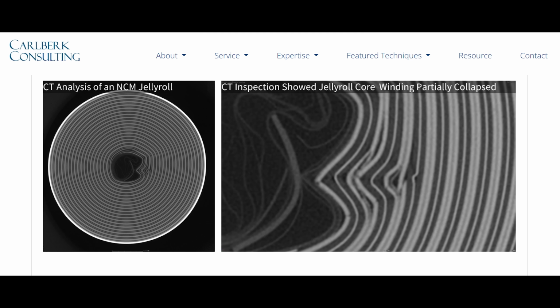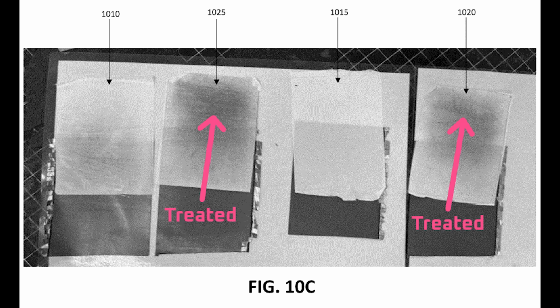If the electrolyte was able to wet the electrode without those pressure changes, it could maintain the pore integrity and therefore stiffness. Second, that whiplash could also push and pull on the inner spiral of the jellyroll. That, again, could be avoided by reducing the vacuum and electrolyte injection pressure. Third, as we'll see later in the video, the plasma treatment process causes the electrode to stick to the separator, which effectively glues the entire jelly roll together so that it's less likely to unwind.